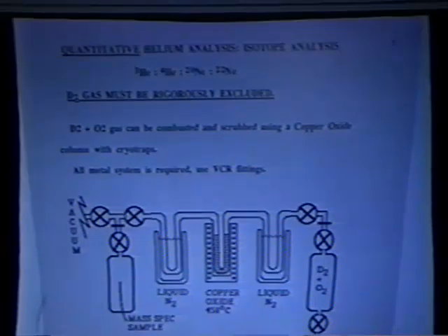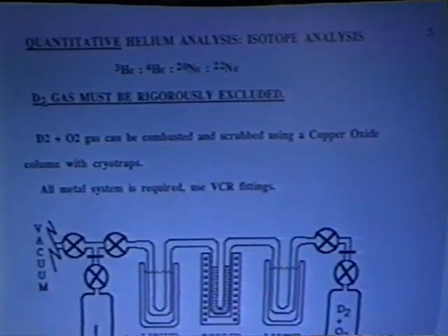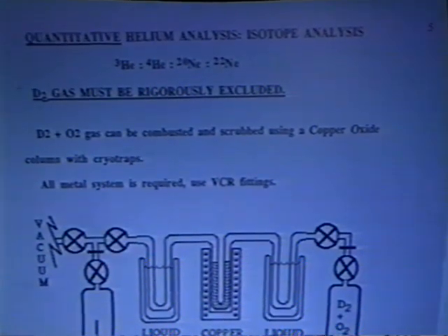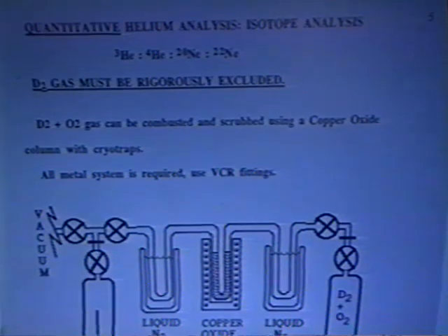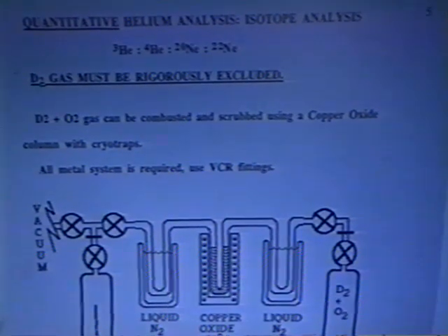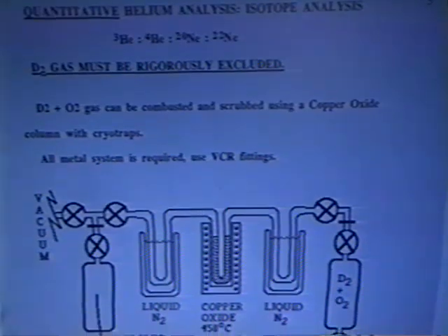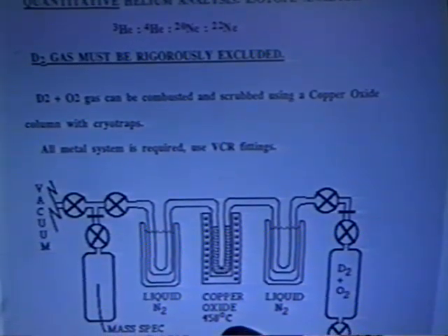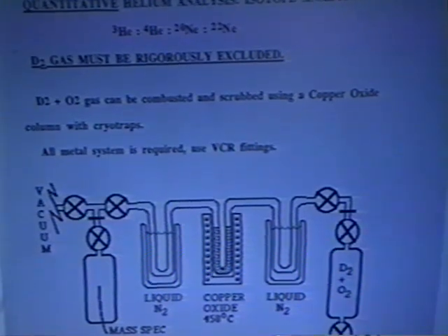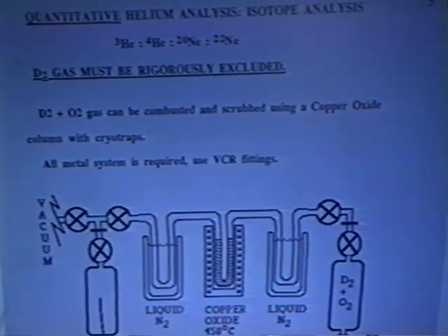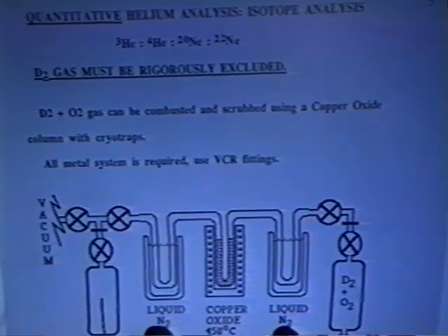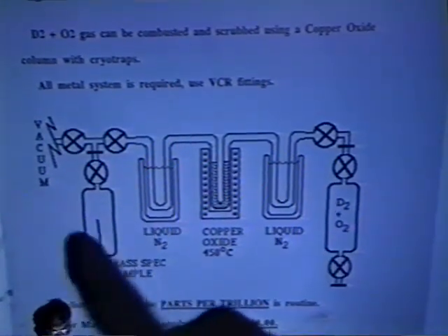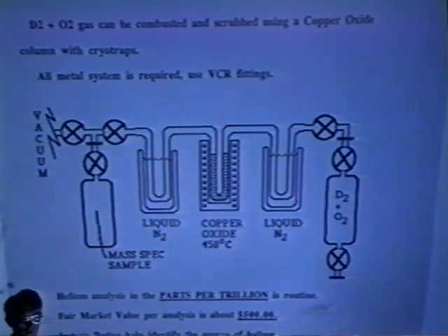Well, you want to do a quantitative helium analysis. That means you're going to use a fancy mass spec. You're going to be talking with people who do helium-3 analysis for a living. That means you're going to get rid of the deuterium. The way you get rid of the deuterium is you burn it up. There's a copper oxide column heated to 450 degrees C, thereabouts. Then the deuterium is now D2O. You trap the D2O with liquid nitrogen traps. So you take your sample into the gas system, burn it up, get D2O, trap that out, and store what remains in the metal flask.